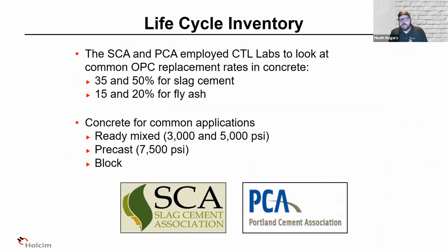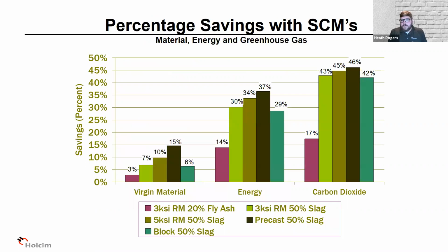So the Slag Cement Association did some testing. They put together 4 concrete mixes and looked at how much energy was used to make those concrete mixes, the total energy used. They looked at a 3,000 PSI, a 5,000 PSI, and a 7,000 PSI precast mix, and then a block mix. If you go to the next slide, you can see basically the savings of virgin material, energy, and carbon dioxide by replacing some of the Portland cement with a supplementary cementitious material. This chart is showing fly ash and slag, there are other things you can do, as we're going to talk about today.